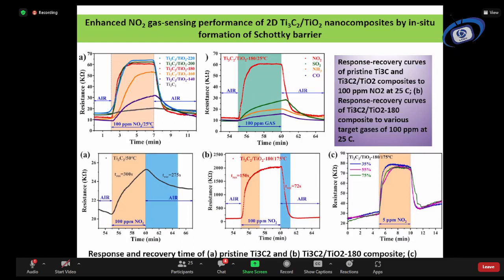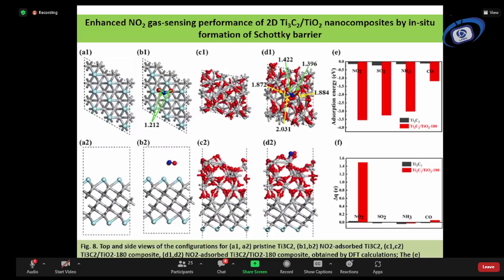And also we tested our sample for different humidity, because these gas sensors are badly affected by the humidity effect, because they adsorb oxygen on the surface of the molecule on the gas sensor during the experiment. But after we fabricate the device, of course the environmental factors affect it very intensively. And this is a simulation we have done on both. We have also compared the simulation results and the experimental results. You can see both in figures E and F. They show a maximum response even for the simulated one, and also of course the experimental one, because that has been experimentally proved, and it gives a very good adsorption energy, and also ultimately high response for nitrogen dioxide gas.